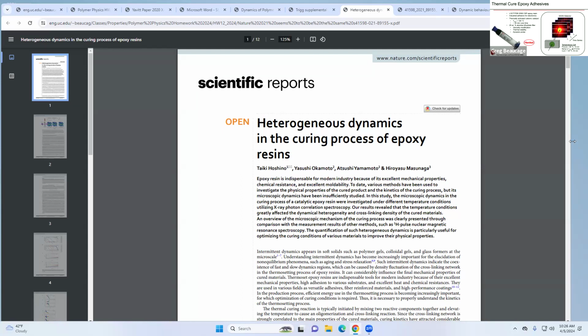But basically, this is an industrial adhesive. One thing that's important about it is it's got a high volume fraction of these aluminum trihydrate filler particles. Those are in there to modify the viscosity and also play with the thermal stability, so they're an actual functional component of the material. But in this case, they're going to be our dynamic probes. We're going to be watching how those fillers move around in the matrix as it's curing. That's a really important part.